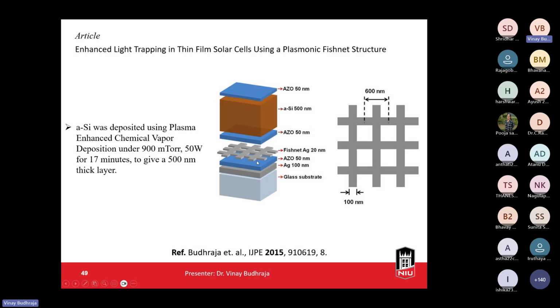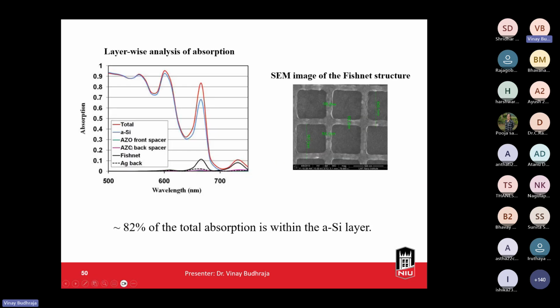That's why we give the name fishnet Ag, and the width of those lines is up to 100 nanometer, and the center to center spacing is 600 nanometer. In this case, the amorphous silicon was done using plasma enhanced chemical vapor deposition under 900 millitorr at 50 watt power for 17 minutes, and we grew around a 500 nanometer thick layer. And overall, the advantage of using the fishnet was clearly observed in the absorption measurement. This was done from ellipsometer, and this graph shows the effect of individual layers, and the amorphous silicon is responsible for around 82% of the total absorption within the amorphous silicon layer.